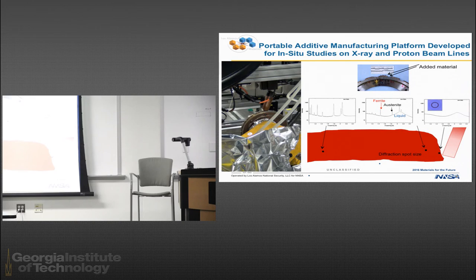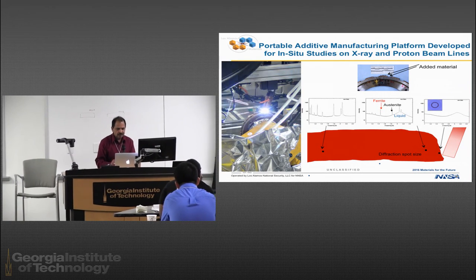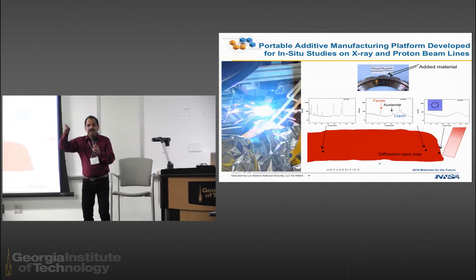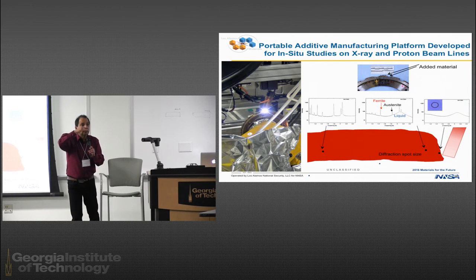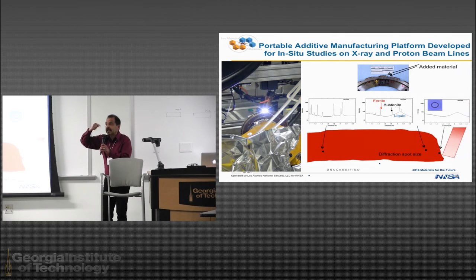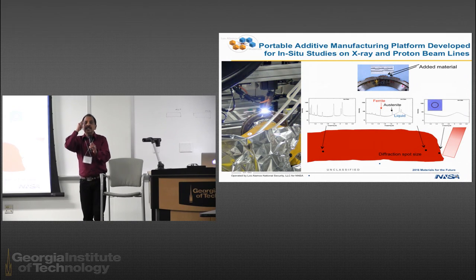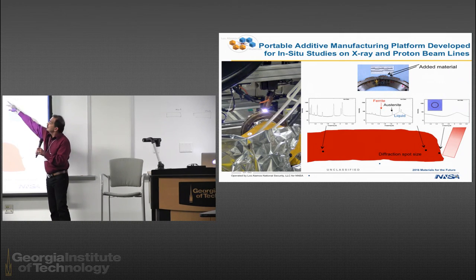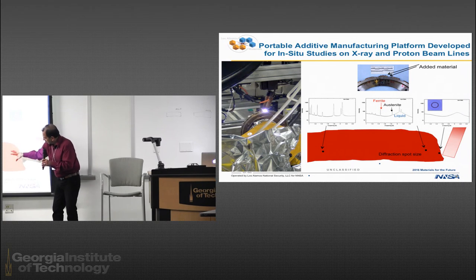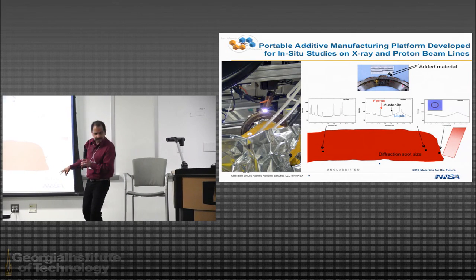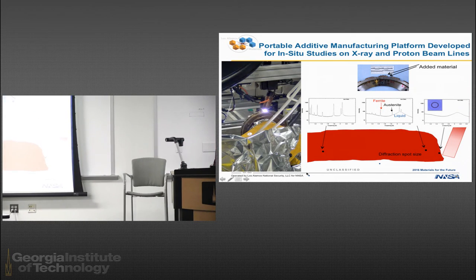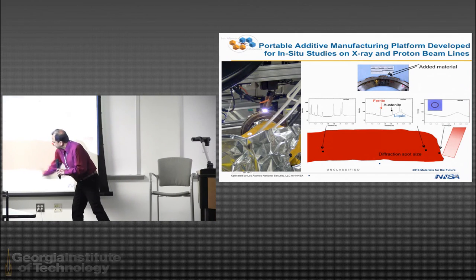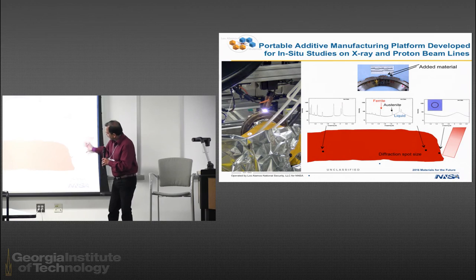So this is laser welding, and you should see it coming. So the wheel is moving. You've got a wheel. It's moving around at a certain rate, and you're laying down material. Okay, so there is a torch there that's laying down material, and what you've got is a light source that is going to interrogate what's happening to the material. It's all in situ. So this is the sort of deposition, and this is the wheel that's moving. There should have been something at the bottom, which didn't come out. Okay, that's fine. So this is sitting on a wheel that's actually moving, and this is the torch.